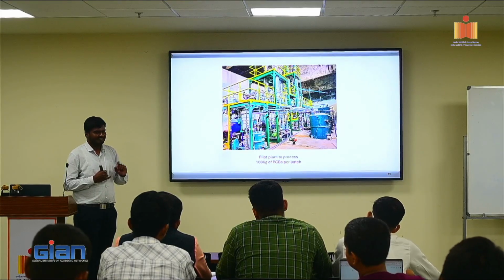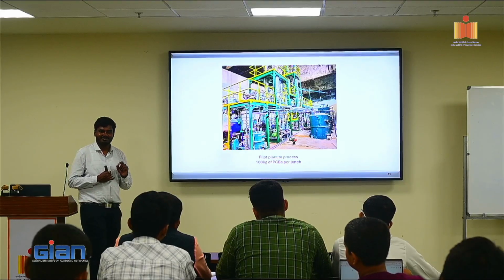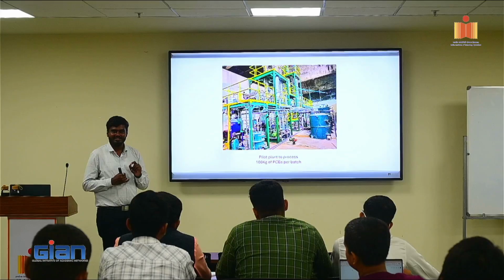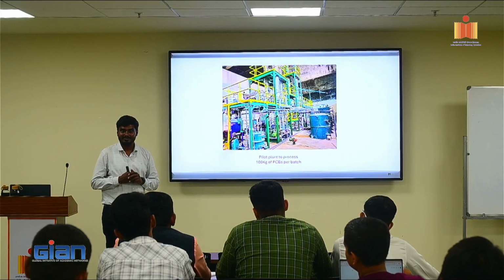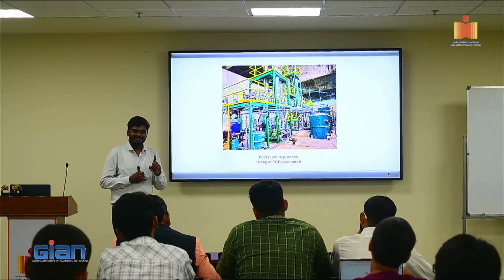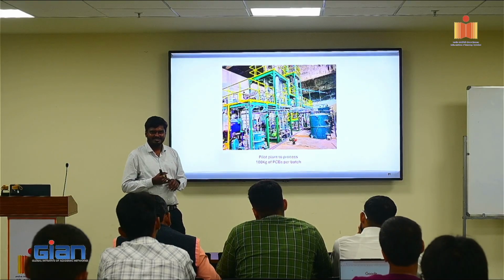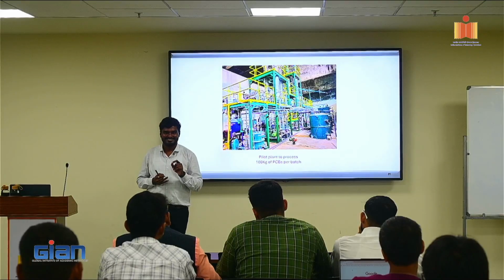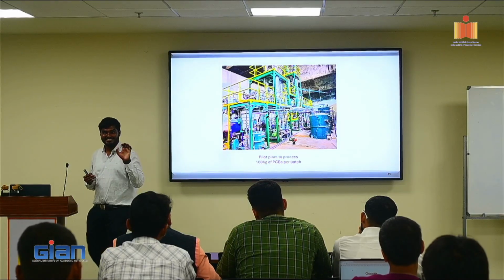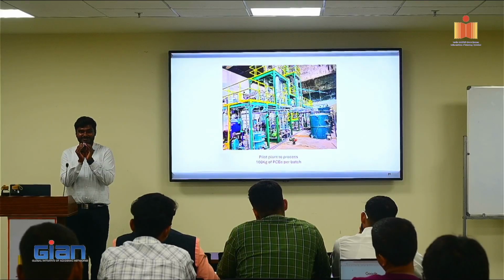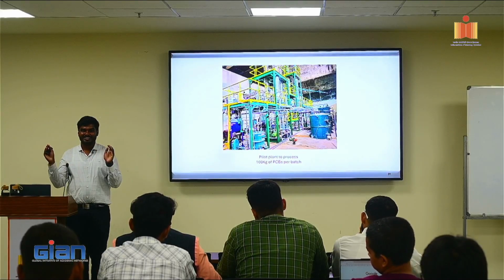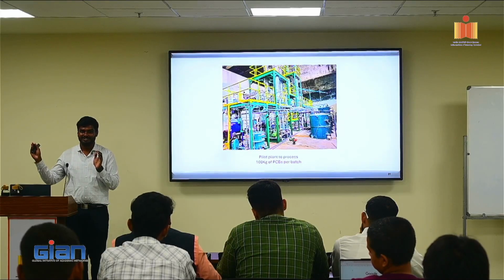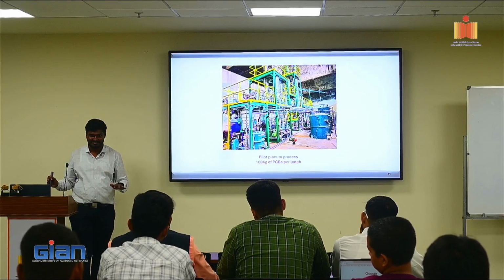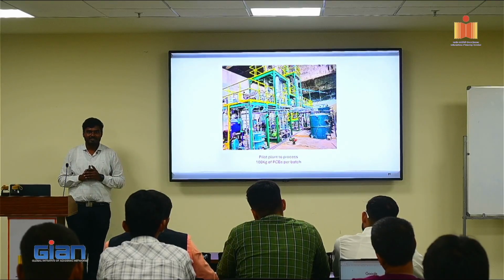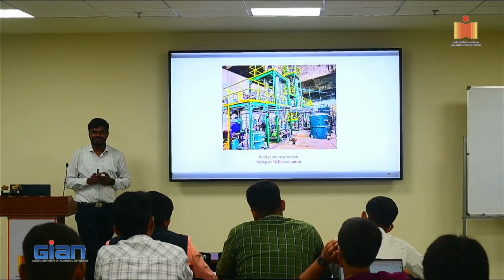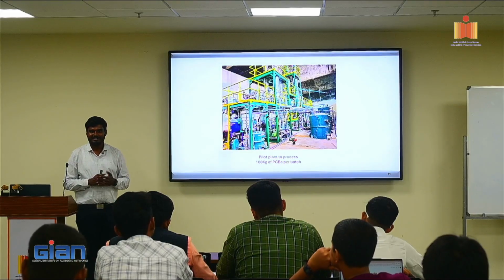Then they said that for one of their applications, they were using copper nanoparticles and they were buying 1 kg of copper nanoparticles for 1 lakh rupees. 1 kg of copper is around 800 to 900 rupees, whereas 1 kg of copper nanoparticles is 1 lakh rupees. But with certain terms and conditions. Those nanoparticles have to be of uniform size. If they are polydispersed, ranging from 10 nanometers to 200 nanometers, then the price will definitely go down. Then they told us they are already buying copper nanoparticles. Can you convert copper nitrate into copper nanoparticles?